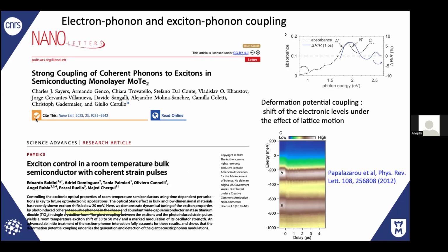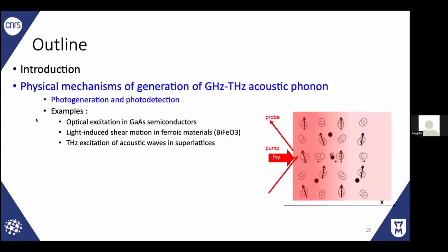As well, you can play with electron-phonon and exciton-phonon coupling. I will tell you a bit more later what the deformation potential is, but strain can modulate the bond distance, the interatomic distance, so you can change the overlap integral, so you shift the energy of the electronic level. And here, this is the exciton band that shifts as a function of time due to the phonon. So you can play with the electronic level with this phonon, and also, just for basic physics, come back from that case, for example, to the deformation potential parameter. I will tell you a few words about what the deformation potential is now, in that part where I would like to come back to the physical mechanism of generation of this phonon.